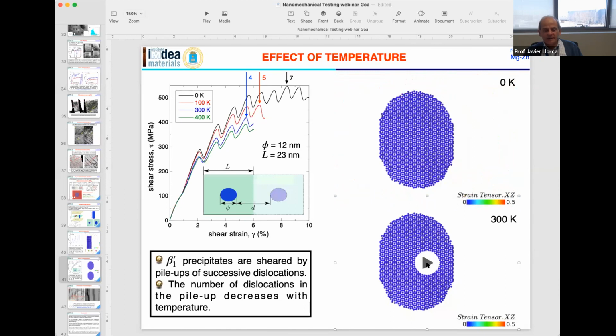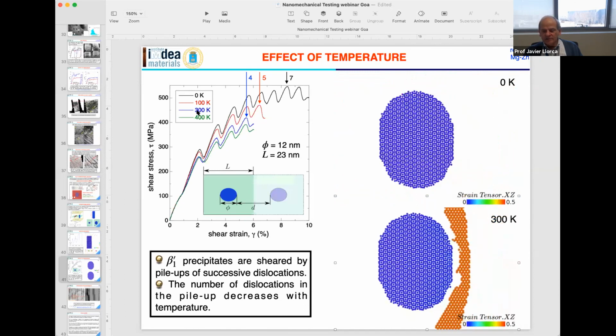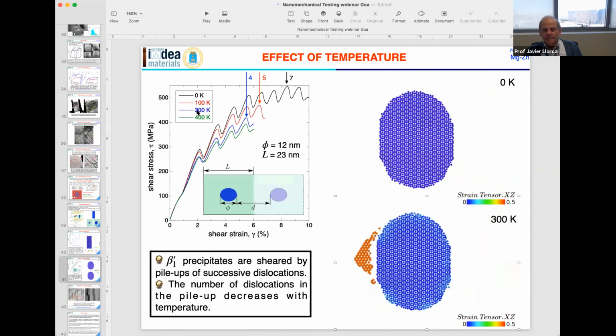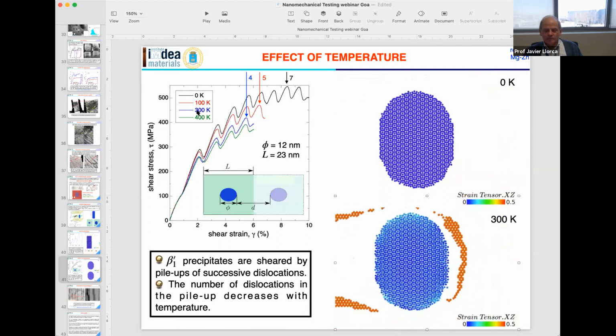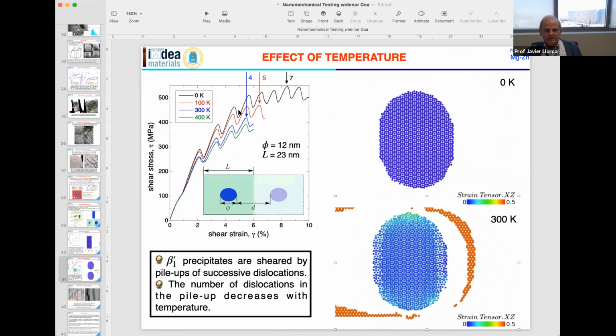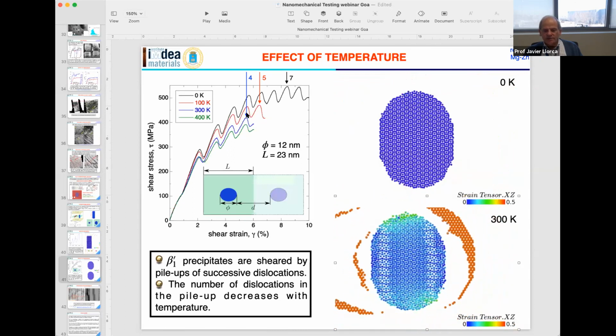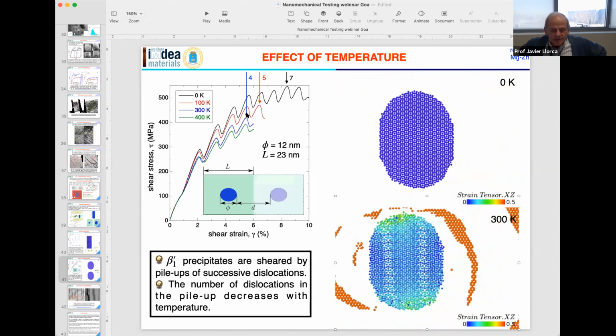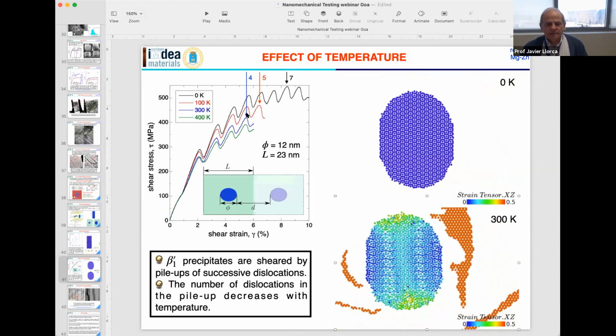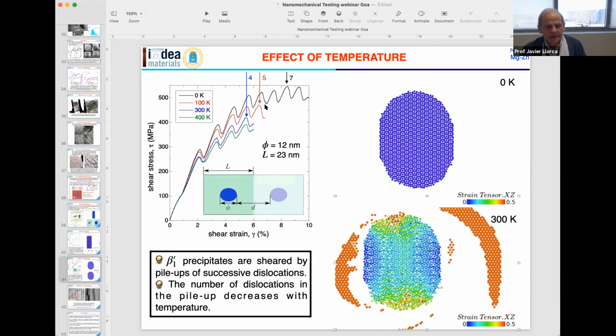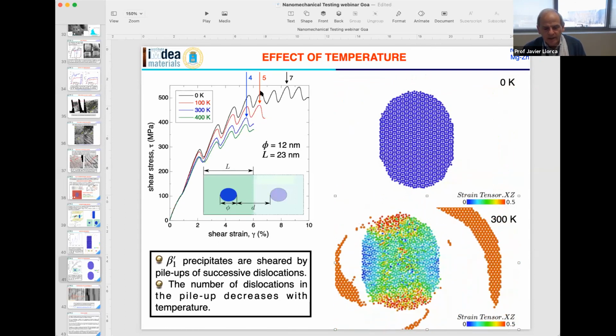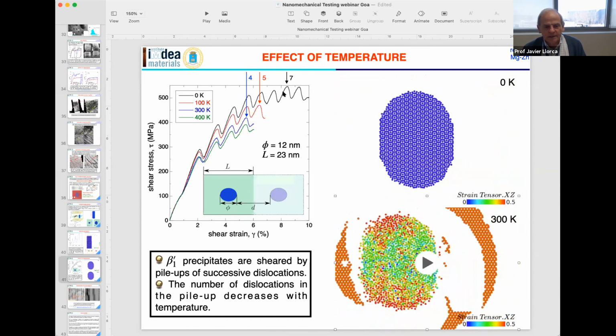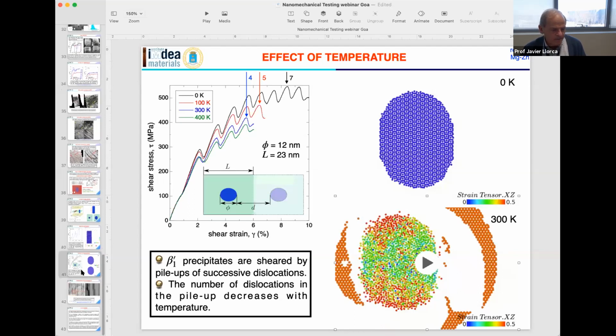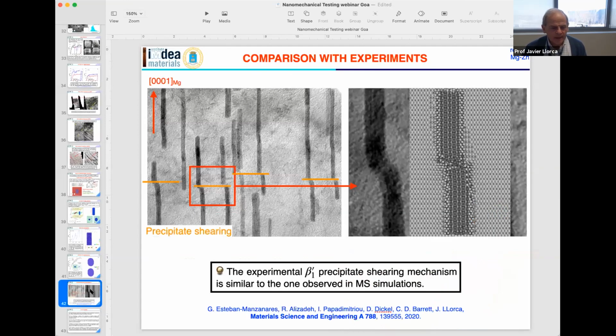This is what happened at 300 Kelvin, the blue. So the first dislocation passes, the second dislocation passes, the third dislocation passes, and then when the fourth dislocation passes, the precipitate is completely sheared. So what you can see here is that dislocations are able to shear the precipitate, and the number of dislocations that you have to pile up in order to shear the precipitate decreases as the temperature increases. There is a strong effect of temperature on the critical resolved shear stress. Actually, what is interesting is that, again, we are going to go to the presentation mode.